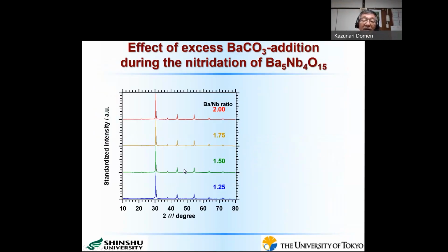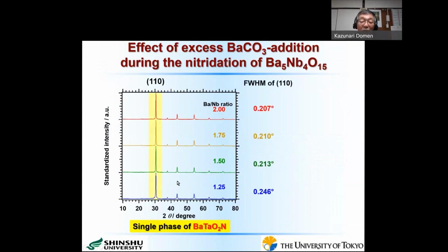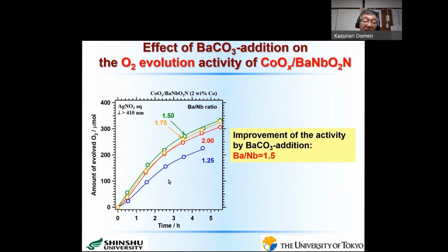Then this is the XRD pattern when we change the barium to niobium ratio. In all cases, as you see, the XRD pattern always shows barium niobium oxynitride. Then when we increase the barium content, the XRD peak full width at half maximum becomes narrower. That means that with the increase of barium content, the crystallinity is improved. However, when we examine the activity of oxygen evolution, as you see here, when we move from 1.25 ratio to 1.50, we obtain the optimum activity, but further increase of the barium decreases the activity like this one.